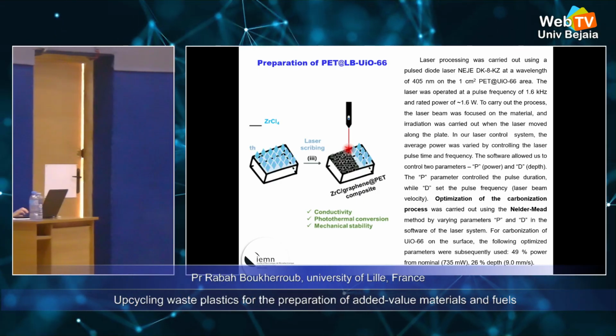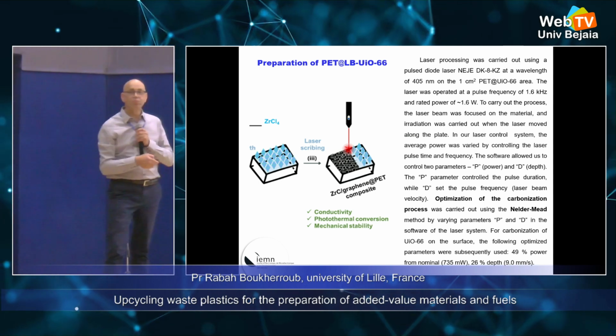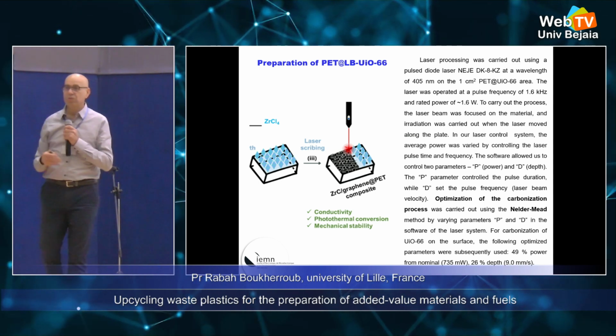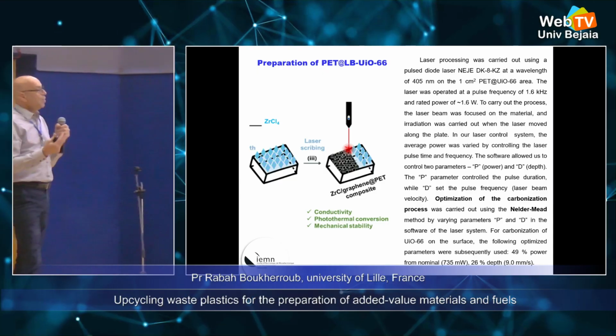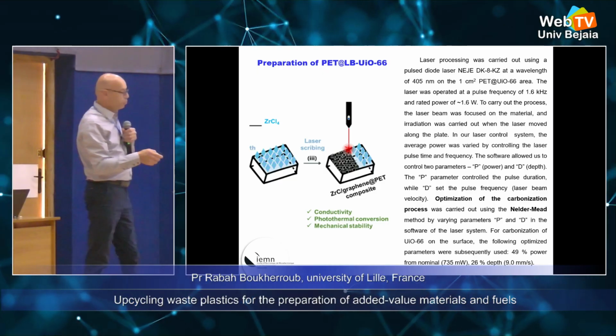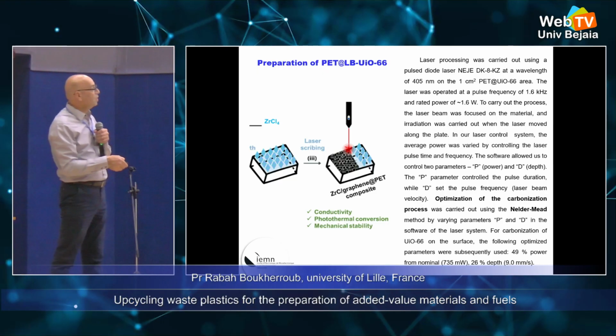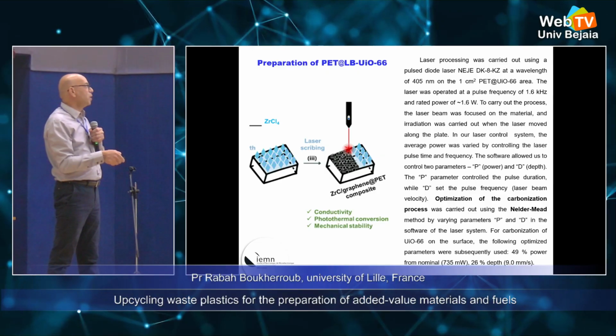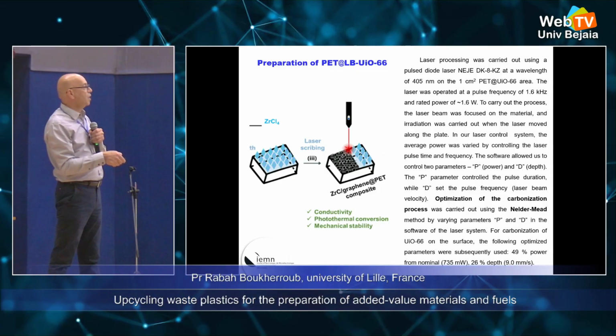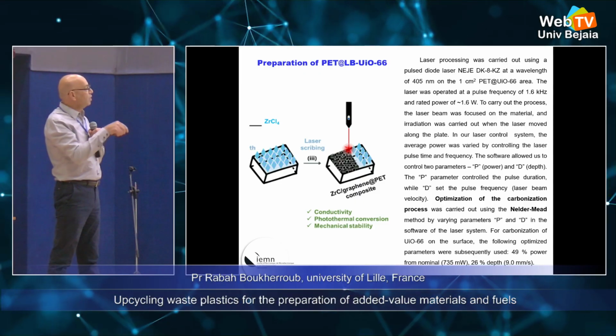Then we have the plastic MOF, and we took a small light emitting diode laser, which is very cheap. You can buy it for a few tens of euros from China. Of course, the problem is that you're limited by the power. You only have 1.6 watt. So you have two parameters you can play with, the power and the depth, and you can write directly on the MOF.